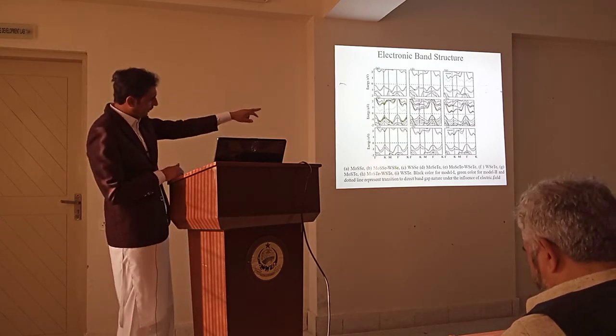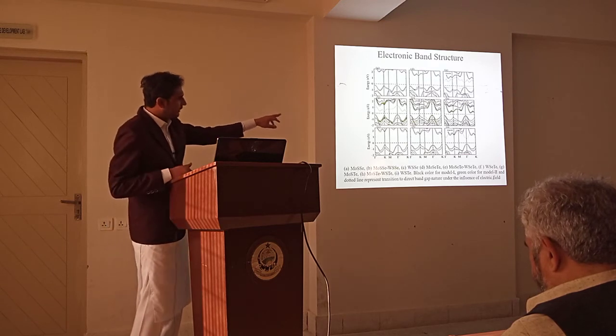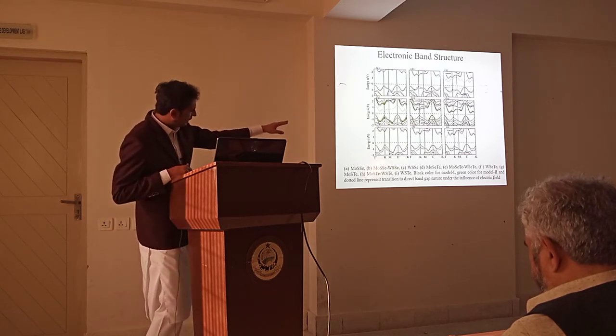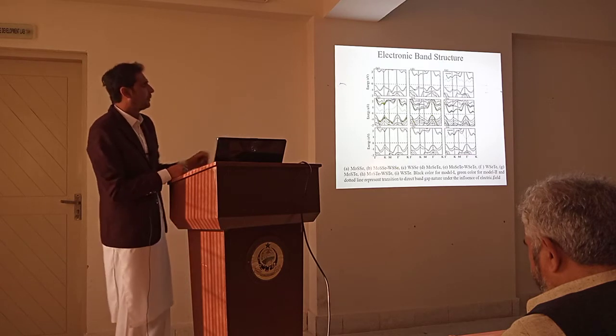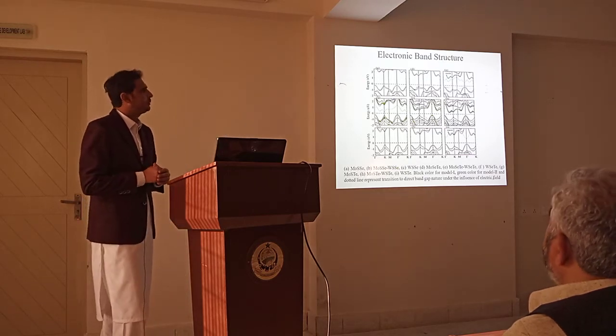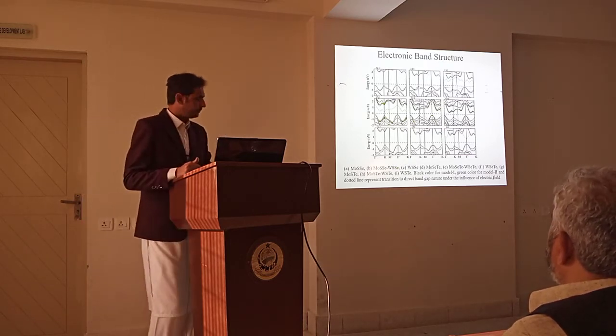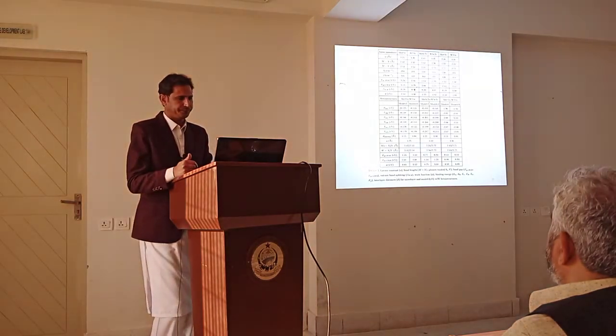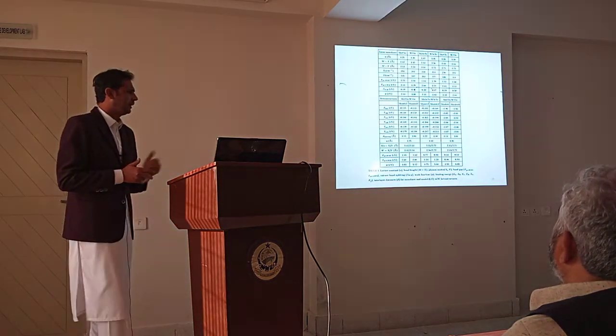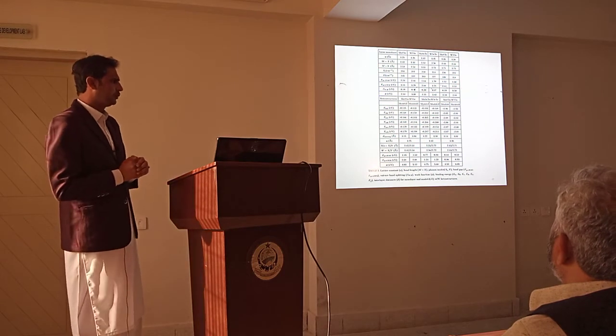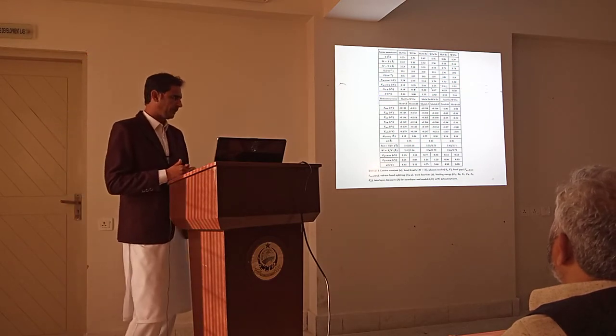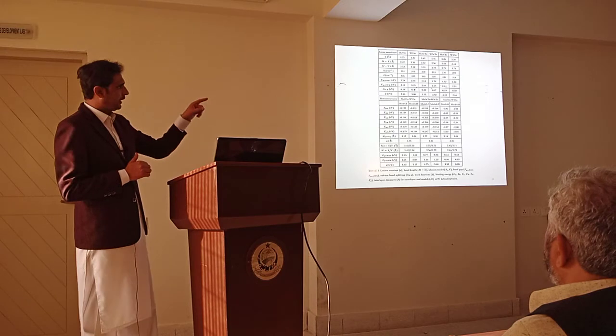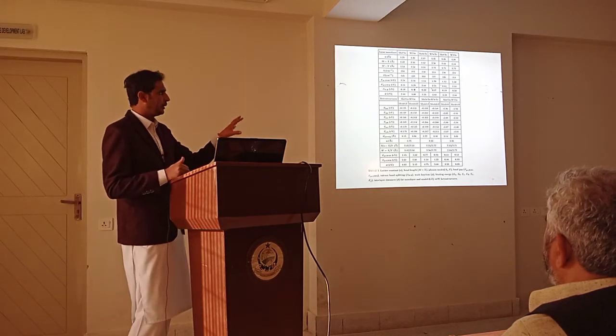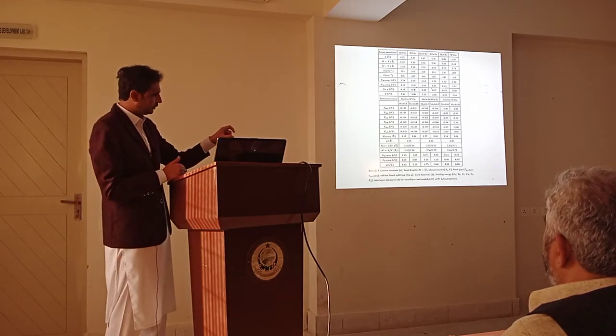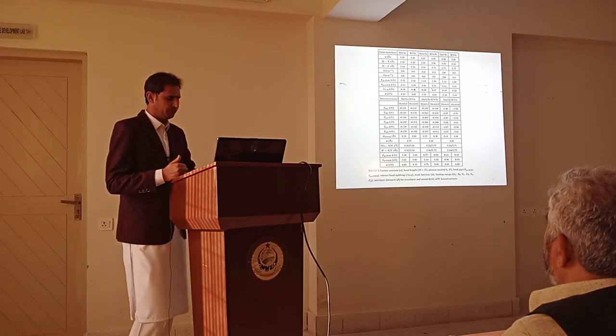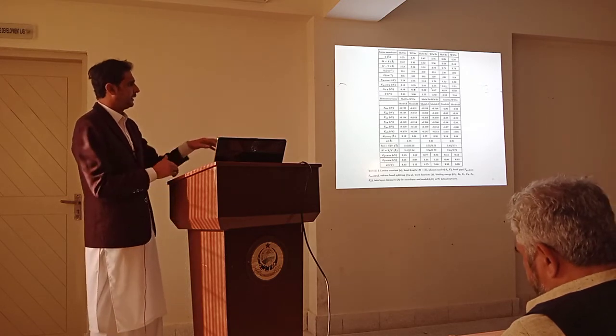Now, the heterostructure also has an indirect band nature, but by applying an electric field, it converted to direct band nature. This is a calculated table for lattice constant, bond length, and phonon modes, which we also compare for MoSSe, which is from an experimental paper. Our phonon modes are comparable to those in the experiment.